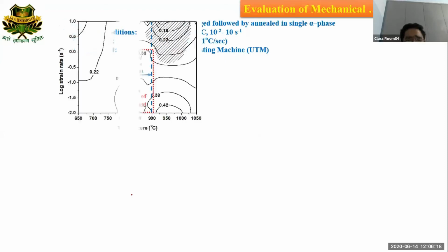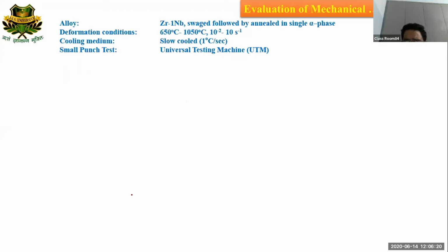Now I'm going to show you another unique kind of work with the help of this thermomechanical simulator, because in the case of the thermomechanical simulator you are using a 10 mm diameter and 15 mm height sample. So you can assume what will be the size of the deformed sample. Very small at the end, and from that deformed sample it is very much difficult to make the tensile sample. Even a miniaturized tensile sample is very much difficult. We have tried but could not succeed.